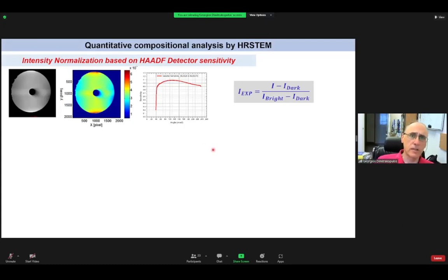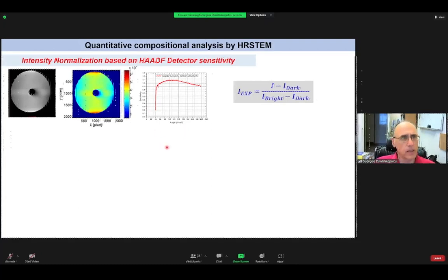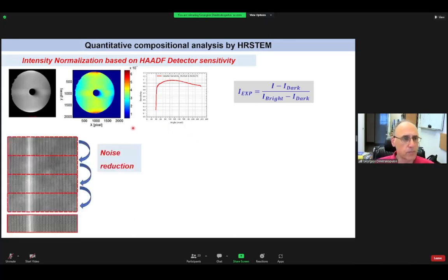So now I would like to go in a little bit more detail about compositional analysis with high resolution STEM. One thing that is a must that we must start with is that we need to do intensity normalization. And for this purpose, you need to take into account the sensitivity of your detector, of your high angle annular dark field detector. So first you start with this step. This has been very well known and developed by people like Rosenauer and others before him.